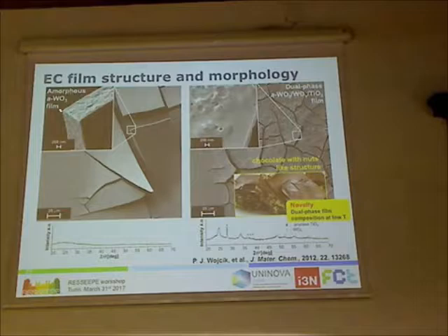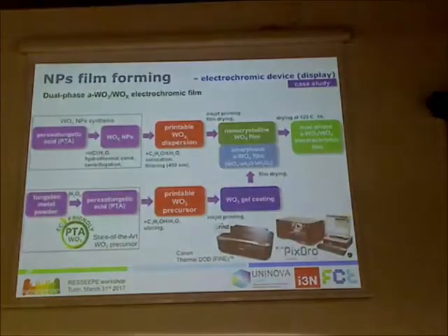You can create these tungsten oxide layers that can be amorphous, or can have what we call a chocolate with nuts-like structure, which is basically a dual phase. You have an amorphous matrix where you have small crystals of tungsten oxide. So you have a mixture of amorphous material with crystalline material, but all are tungsten oxide. I will explain later the advantage of using this.